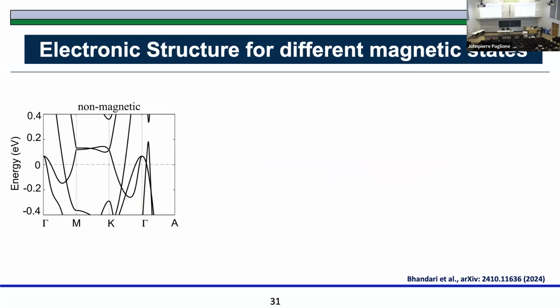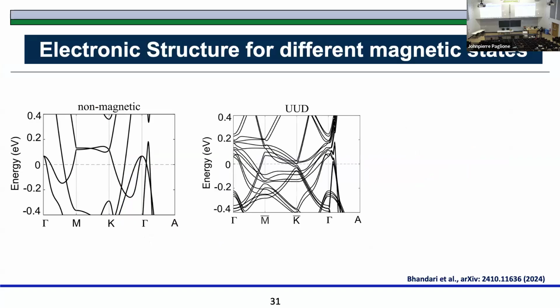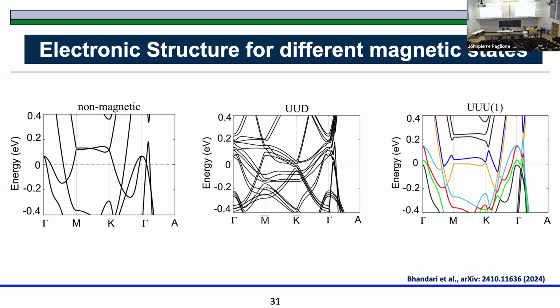Okay, and then some one-dimensional flat bands also, some reminiscence of the Kagome system that I showed you earlier. Okay, now your system is ordered, and then it becomes root 3 by root 3, your band is all messed up, right? So it's not as nice as this one. But when you go into that final state of this magnetic structure, then this is the band structure for that particular case. You basically recover these bands.